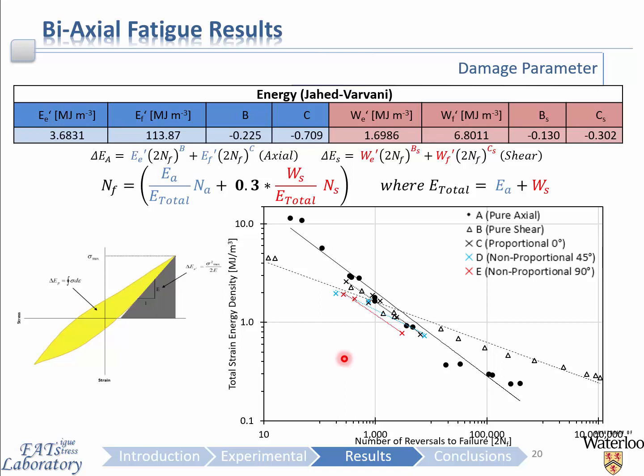The quantities that are required for the model are the plastic strain energy density, which is signified by this yellow area enveloped in the hysteresis loop here, and then the elastic strain energy density, which is this gray triangular area here. The model takes the form of a Coffin-Manson relationship, however, instead uses strain energy density versus number of reversals to generate the calibration constants that are required.